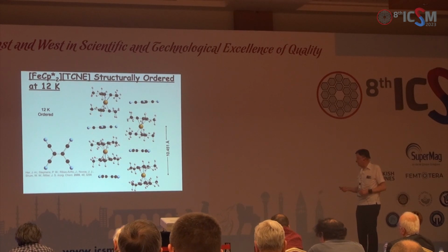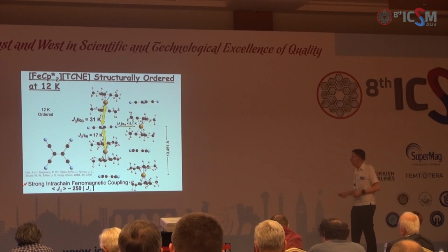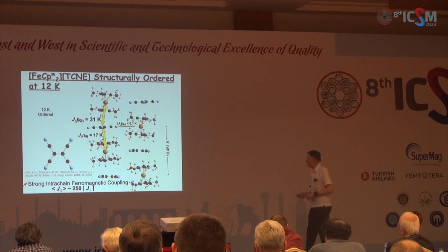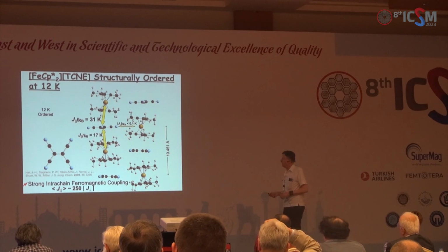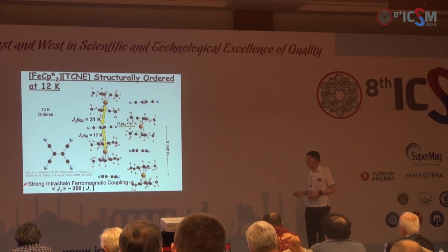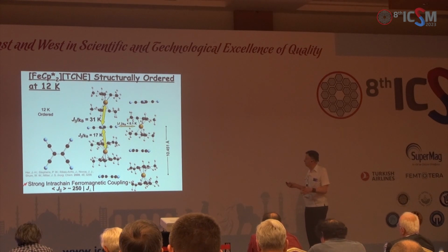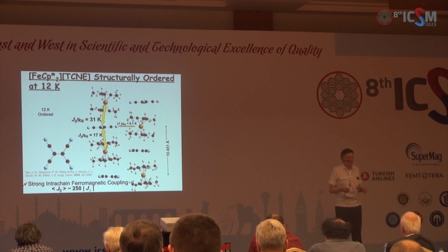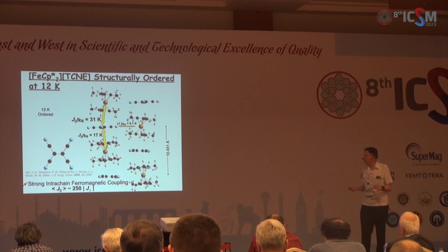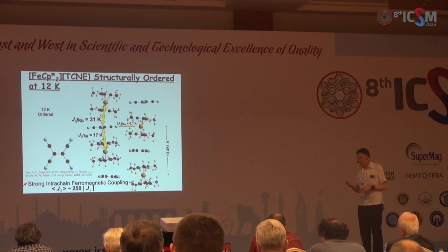Some computational analysis indicates the intra-chain coupling is ferromagnetic and a factor of 250 times greater than the interchain coupling for it. So it's mostly one-dimensional, which is a bit of a problem for some people, but the fact is it is three-dimensional in its structure, and it is observed to magnetically order for this material.